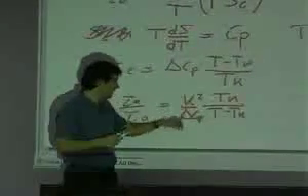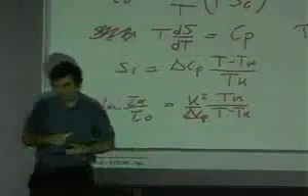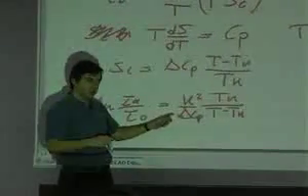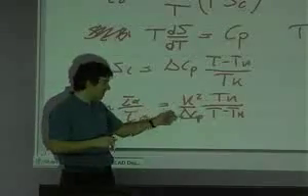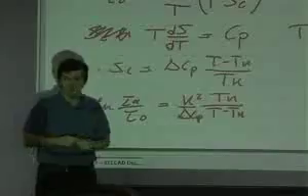More or less. And then the third thing is that if you look at this expression, log of tau alpha divided by tau 0 times this, of course you get the Vogel-Fulcher form. And if you remember, I guess you must have seen this in the first lecture, you can define a fragility of the liquids, and the fragility is estimated by the prefactor, which is here. So now you get a clear relationship between the fragility of a system and the specific heat jump.